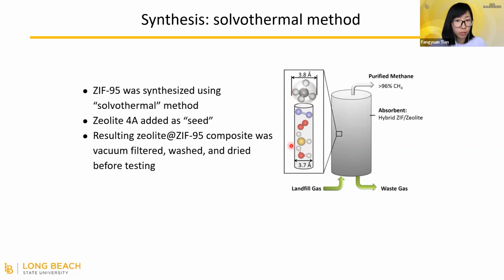We're thinking that if we could find a porous material with an aperture around 3.7 angstrom, then those impurity gases can enter and be trapped there, except methane. So this is like a funnel, based on the molecular sieving process. We can use ZIF-95, which has approximately 3.7 angstrom per aperture, to trap all of these gas molecules.